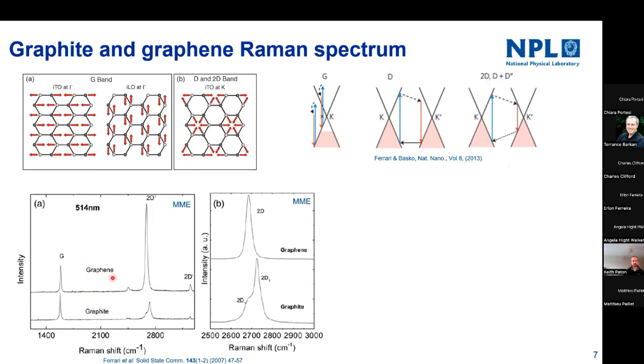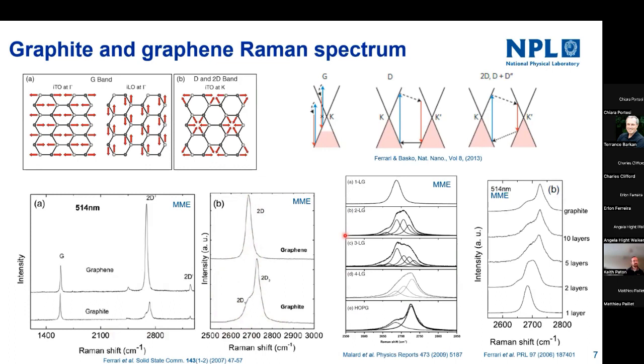There are clear differences between the spectrum of single-layer graphene and graphite, primarily in the shape and position of the 2D band. For single-layer graphene, you see a symmetric peak with narrow width, whereas for graphite you see a distinctive shoulder on the low-frequency side of the 2D band, generally fitted well to two peaks. As you go from single-layer to bilayer, three-layer, and up to 10-layer and then graphite, the shape, position, and width of the 2D peak evolves. Beyond 10 layers it's very difficult to distinguish structural information about your material.